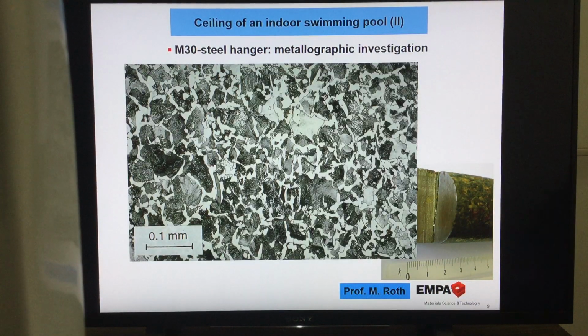This is just to show you the microstructure of this 8.8 steel. It's a ferritic pearlitic steel, and you can even judge a little bit the carbon content of the steel. You see here, these are all our pearlitic parts. You see here the stripes of the pearlite, and between them the white one, this is the ferrite.